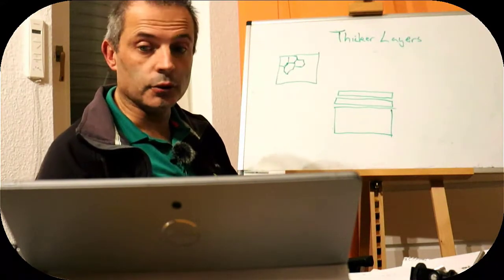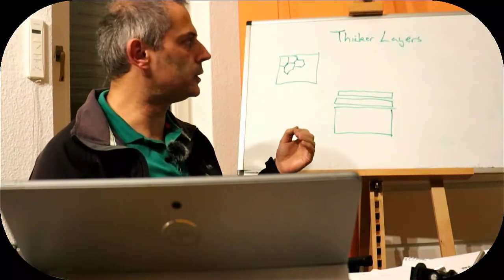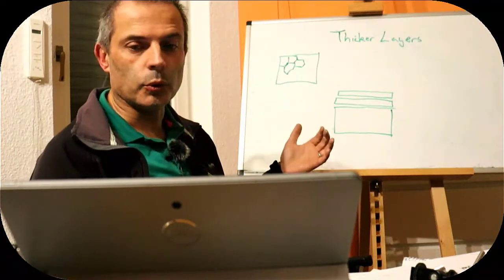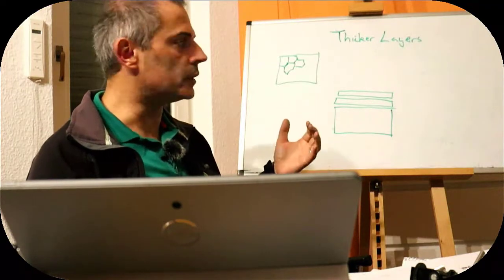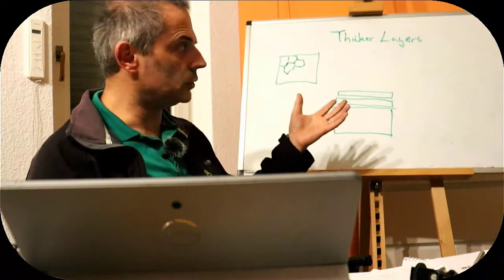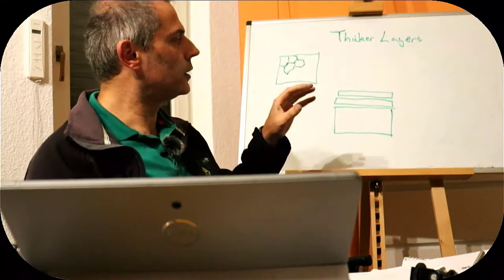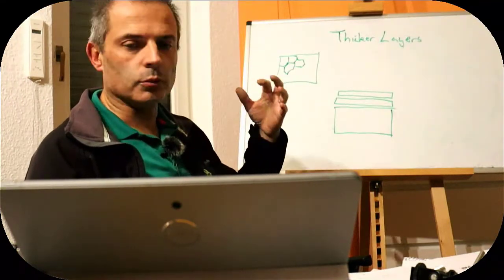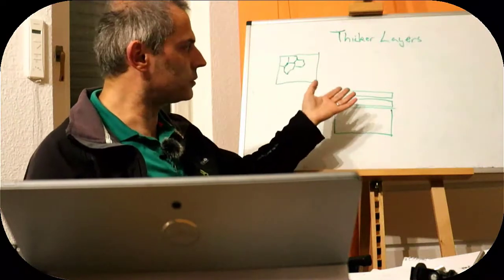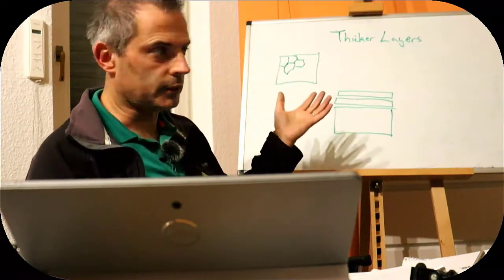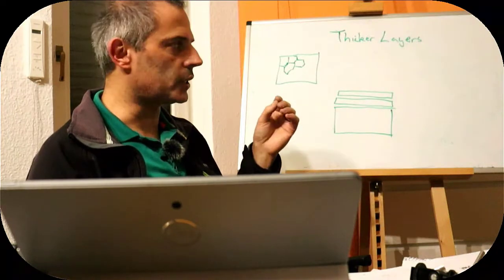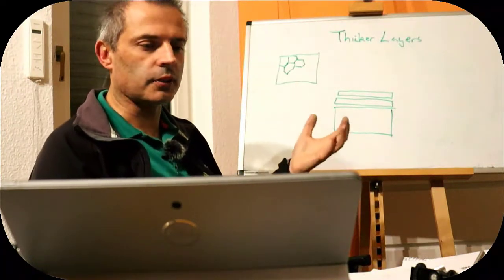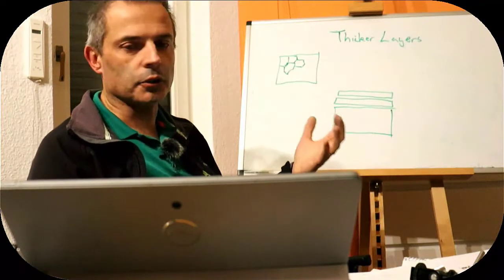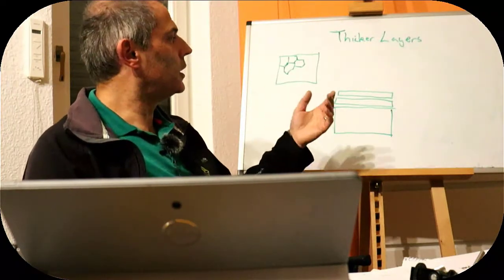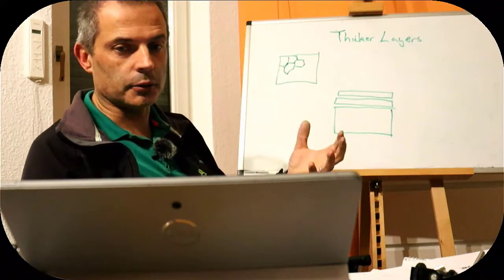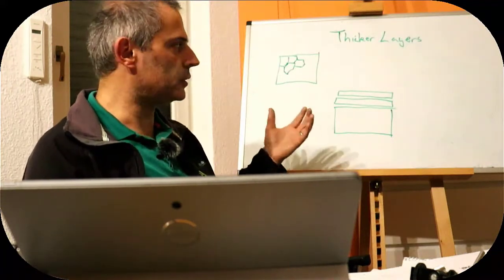One way around it is to not make a thicker film, so to just have a thin coating and to use that. That would be what we would see in things like consumer grade drill bits and cheap cutting tools, because then we've got a thin layer that's hard. It will work very well, but then it will wear off because it's not very thick, and then it will stop working. That's ideal for tools that are intended by the manufacturer to be disposed of and then you buy a new one. It's not if you want a premium tool, and so typically we will have a thicker coating or some kind of better way of doing it.